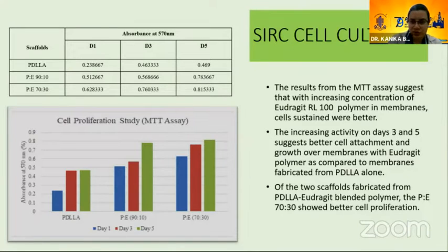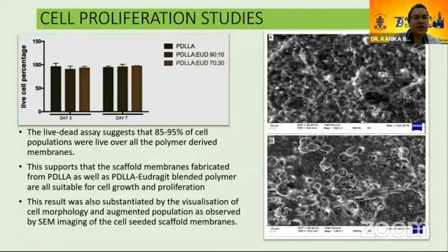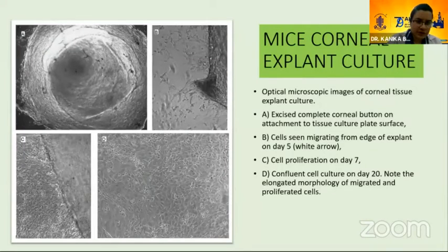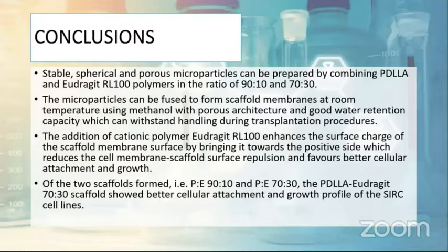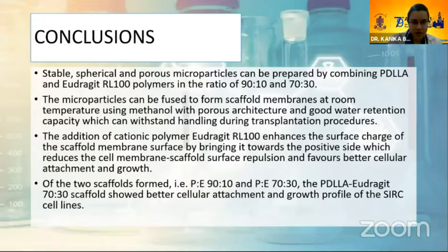SIRC cell culture also showed the same, and we could see the growth from day 1 to day 5 increasing, and 70-30 showed the best. We also tried corneal tissue explant, but because of time constraints, we could not complete it. I would conclude that stable particles can be formed in ratios of 90-10 and 70-30, and these can be fused into desirable scaffolds, and these can be good for cell growth.